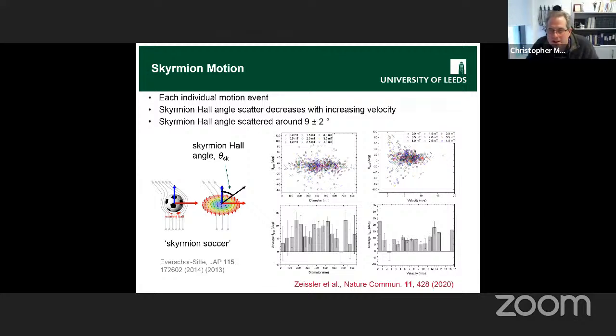But what you can see is there's a big change in the spread. So over here, the angle tends to be not too far from that 9 degrees, whereas here, at these very low speeds, the angle can basically be almost anything. It goes from kind of -90 to +90.